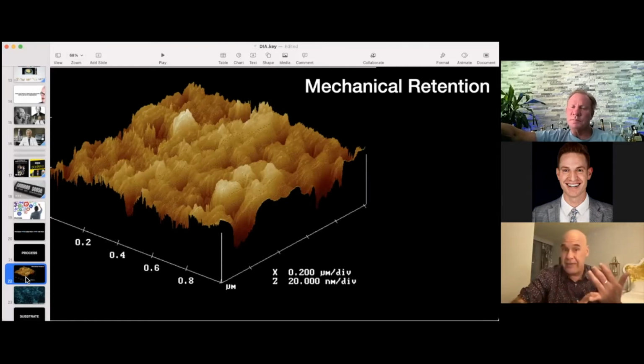So enamel, you have to etch with phosphoric. Lithium disilicate, you need to etch with hydrofluoric. And zirconia, you need to sandblast. You are going to achieve the same thing, which is mechanical retention. You need to achieve that. And that is the most, not important, but when you think about the bond strength that we are able to generate in a lab, about 70% of your value is all mechanical retention.